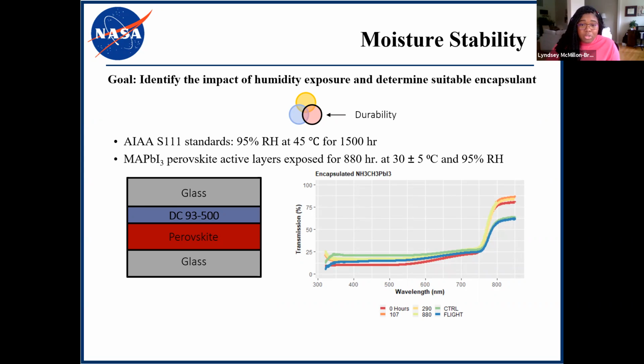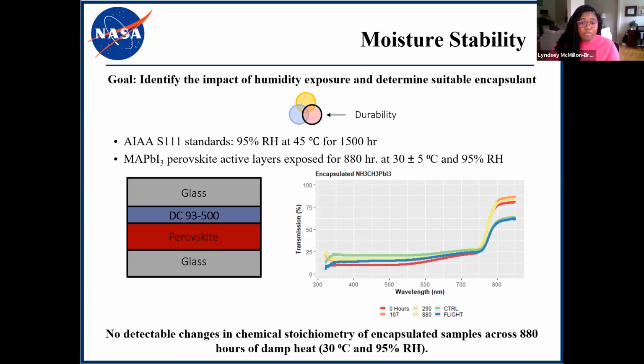There's no detectable change in chemical stoichiometry of these encapsulated samples. I can say that because we don't see any new features arising in the transmission spectra. So from that, we can conclude that there are no changes after 880 hours of damp heat. So at this time, at 880 hours into the experiment, we randomly selected 2 samples from this experiment and sent them for a flight test.